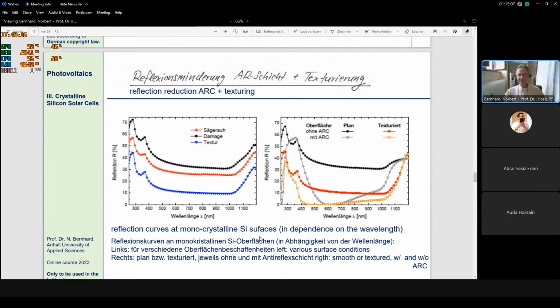If you compare it with the black curve, it's really a very, very big improvement. As I said already, usually the reflected radiation would be more than 30%. With both together, it goes down to 3 to 4%. That means this is really, in principle, two rather simple measures which improve the performance of such a solar cell very much.